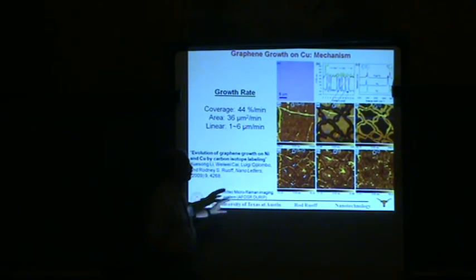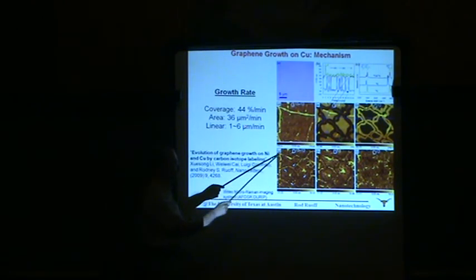Okay. So we end up with nucleation occurring in different spots on the copper, islands growing outward and then knitting together. And there's no more active copper surface, and growth stops at a monolayer. So this is very valuable. It shows us the grain size. It shows us what the grain boundaries look like. And we can also do something called D-band mapping. D-band shows up in a different location, actually around 1340 wave number. And it's an indication of defects such as wrinkles in the film, and also can show where the grain boundaries are. So soon we'll talk about what's the structure of the grain boundaries, and we'll talk about pentagons and heptagons, as Harry did with pentagons for C60.